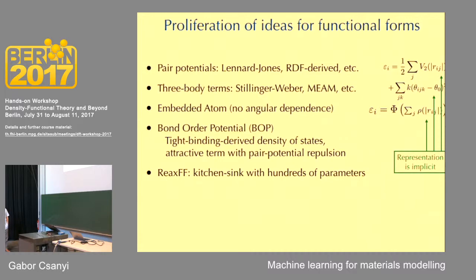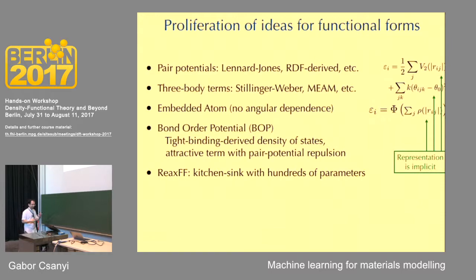Inside these functions, there are representations. The list of all pairwise distances is a representation of atomic coordinates that you plug into a pair potential. One can ask: just from transforming the coordinates into an unordered list of distances, does that involve an approximation? Have you thrown out accuracy? The answer turns out to be yes. And if you don't think about representations separately from the functions, you don't get to ask that question. You can ask the same for the three-body potential — it has angle information, but it's also unordered, and the function doesn't know which angles belong to which distances.